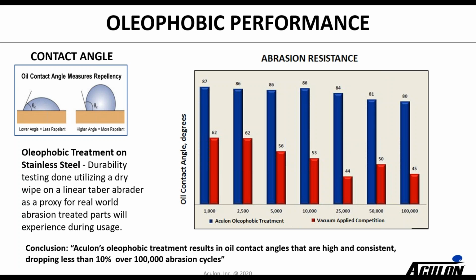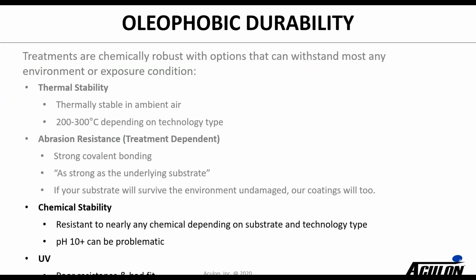In this particular case, we were asked to benchmark against a competitive set, which was a vacuum deposition applied treatment. You can see it starts out oleophobic. As I said, for us, the benchmark starts at 60 degrees. But you can see fairly quickly it drops off and loses its oleophobicity. So obviously, if you've got a substrate that's going to see abrasion, etc., and you want it to last, picking the right kind of oleophobic treatment is critical.